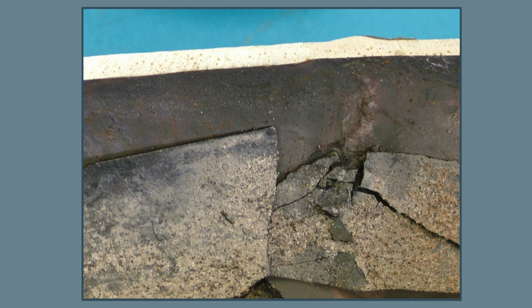Yes. So from this investigation, we saw that a lot of the deposits built up on the inside of the tube, causing increased temperatures. So we would say hotspots. And that's where, again, we have a deposit build-up, and that then influences the efficiency of your boiler. So the guys would run it higher, if that makes sense. And this just feeds the problem. So we had hotspots, which caused this fish mouth forming.